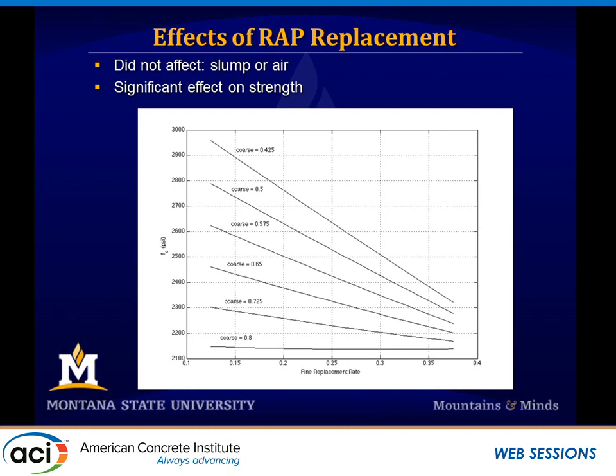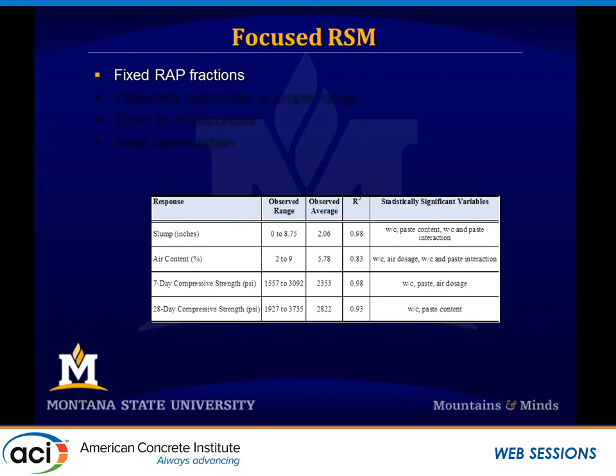This was a surface that was fit to the data afterwards, and it showed us we quantified the effect of including RAP. Right, and with an R squared value in terms of regression of around 95%. So the model fit it really well. It was just off target. So it does bad things to your concrete. And we think that we know that the reason for doing this is that aggregate binder that's on the outside of our aggregates. And when we did our more focused response surface methodology, we fixed the RAP fractions.